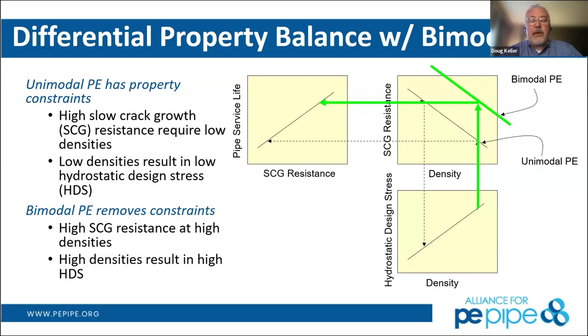What bimodal polyethylene does is it gives us that green line in the upper right-hand corner, which allows us to shift the relationship between slow crack growth resistance and density. That allows us to have a higher hydrostatic design stress and also a higher pipe service life because of the higher slow crack growth resistance. So it allows us to have the best of both worlds, high pressure resistance and high slow crack growth resistance.